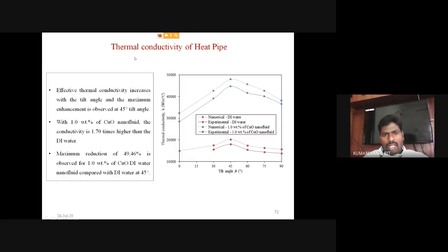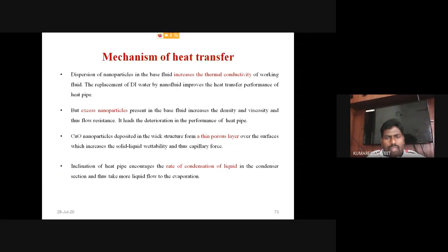Okay, then next, thermal conductivity comparison. You see here the thermal conductivity is also high for the heat pipe operating with the copper oxide nanofluid with 1 weight percentage, and in the numerical results it attained a maximum of 48,000 watt per meter Kelvin. Okay, and next, the mechanism of the enhancement in heat transfer of the heat pipe heat exchanger.